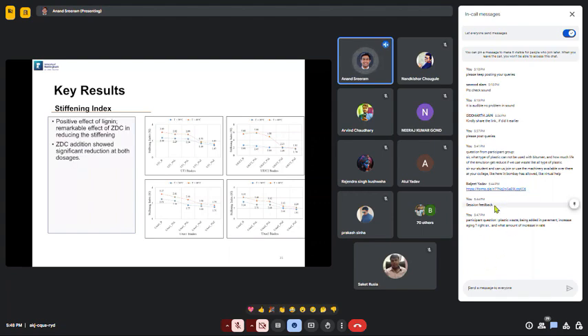Key results from this were that we could see the positive effect of lignin, an antioxidant additive that we added, and we could see the remarkable effect of ZDC, which is a zinc-based additive, in reducing the stiffening, or reducing the rate of oxidation. We could see that the zinc showed reduction at different dosages, at 3% as well as 5%, and we could also see that the stiffening index, or the rate of change of stiffening, which is an indirect measure for oxidation, was around 50% lower when we added these specific antioxidants.